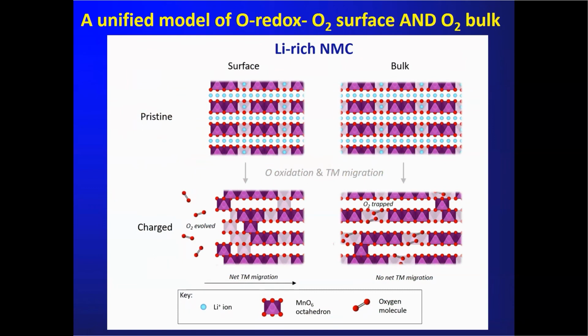Because what this means is that we can have a single unified model for oxygen redox. That when you oxidize oxide ions, unless you have suppression mechanisms that I've just shown, you will favor the formation of molecular oxygen wherever this is possible. And at the surface, of course, it's relatively easy and you can just evolve oxygen. It's more difficult in the bulk because it requires some metal ions to move to accommodate them. But we have a single unified picture now of molecular oxygen being the destination of oxygen redox.